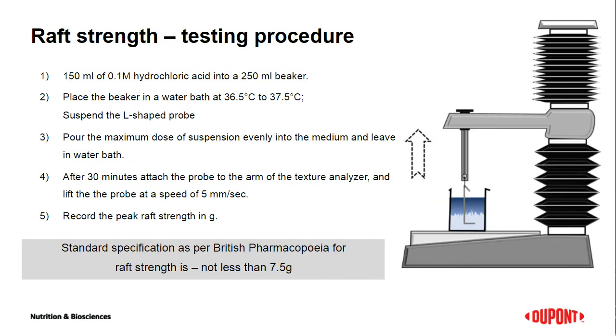The raft strength measurement method involves the preparation of raft by using 0.1 normal HCl as per the British Pharmacopoeia. 150 ml of 0.1 normal HCl is added into a 250 ml beaker and kept in a water bath to attain a temperature of 36.5 to 37.5 degrees centigrade, and an L-shaped probe is suspended in the center of the solution with a support. Once the temperature of the solution is reached, the maximum dose of suspension formulation is added to the solution. It is kept for 30 minutes in the water bath.